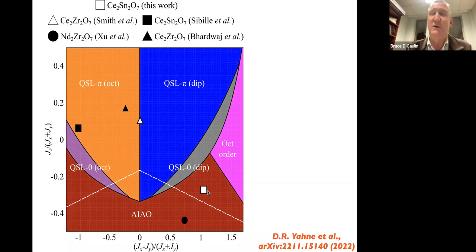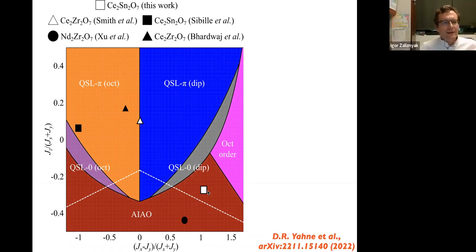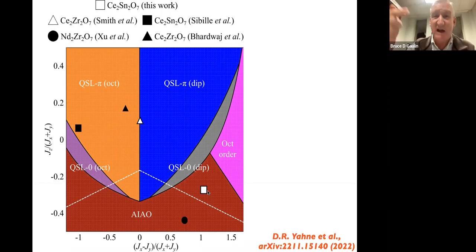But I believe you would take this argument back to what the eigenvectors are of the states that make up the ground state doublet. If you have only MJ equals plus or minus 3/2, then the other possible non-zero component of G has to be 0. Right. Actually, the only way to generate something, if you have MJ equals plus or minus 3/2, is that the symmetry of the threefold rotation means that you've got to skip every third MJ value. So the only other MJ that's allowed for J equals 5/2,